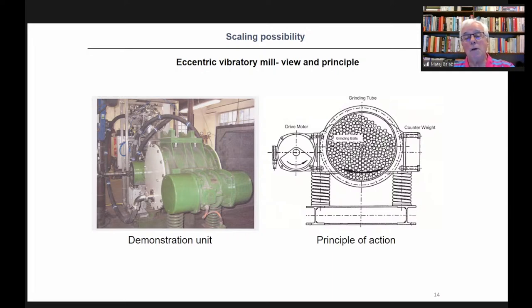So if you have a drive motor on the left side, you need some counterweight, because it is not totally balanced, but you need some difference to obtain good results. Balls, for example, here are grinding balls which fill about 80% of the inner volume of the grinding tube, and it's several hundred kilograms to perform experiments.